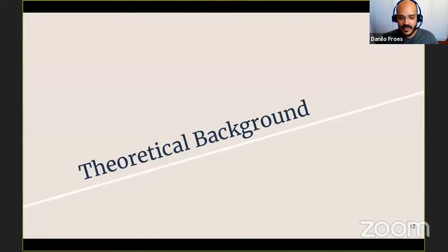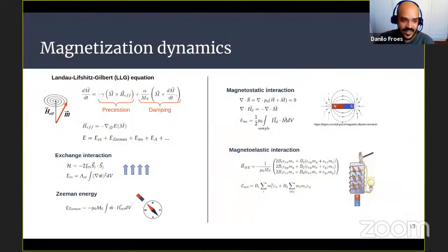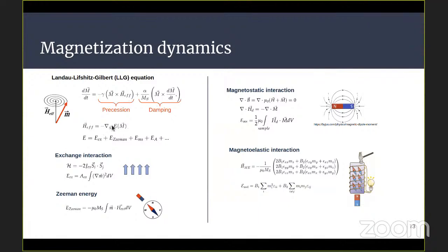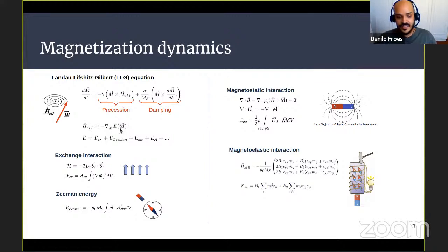Okay, so just quickly talking about the theoretical background, I'm sure you're very familiar with the magnetization dynamics. So we describe the magnetization evolution with the Landau-Lifshitz-Gilbert equation, which has a precession and a damping term. The precession is about the effective magnetic field, which is obtained from the total energy. And this total energy includes lots of terms: the exchange interaction, the Zeeman energy, the magnetostatic interaction, the uniaxial anisotropies, and also the magnetoelastic interaction.